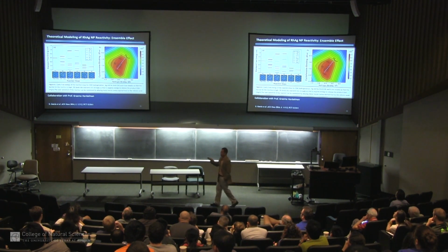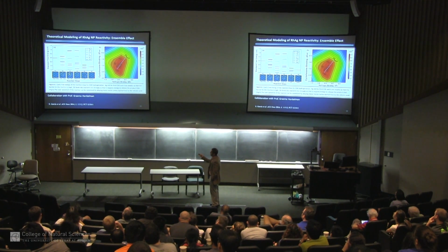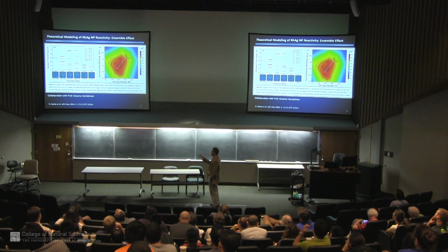I'm explaining this because it's hard to see. Co-adsorption of the hydrogen, so that the H2 splits to give these two purple atoms, which is the two hydrides. One hydride migrates, the second hydride migrates, and then this step is important, it's desorption of the product. If you can't desorb the product, it stands to reason you can't get more reactants down, and that's one of the rate limiting steps.